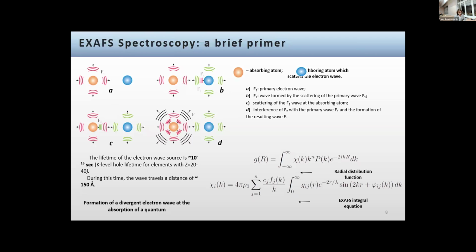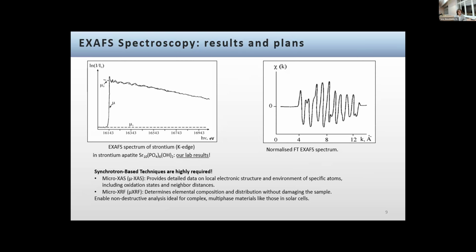Right. So interestingly enough, there have already been some very preliminary, but nevertheless interesting results obtained in our lab in the past. Professor Karbivsky has actually designed at some point a lab-based prototype of the EXAFS experiment. And I find it particularly fascinating that it has obtained some spectra of real materials. Like here you can see the spectrum of strontium apatite. Yeah, it is not the one that was proposed, but still very relevant as an example.